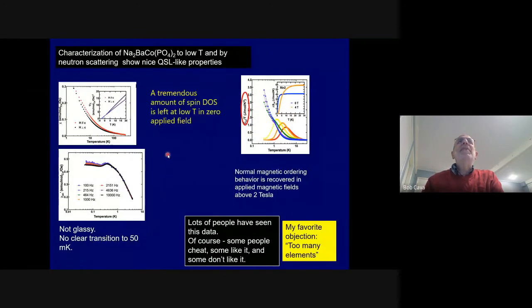The good news about Na2BaCo(PO4)2 is that it never freezes. So you can go down to like 50 millikelvin, and there's never any sign of a magnetic ordering transition. So you have a cobalt 2+, which is a spin one-half on a triangular lattice that never freezes, and only when you put it in a magnetic field on the order of a few Tesla do you see something in the heat capacity that indicates that the spins actually freeze.